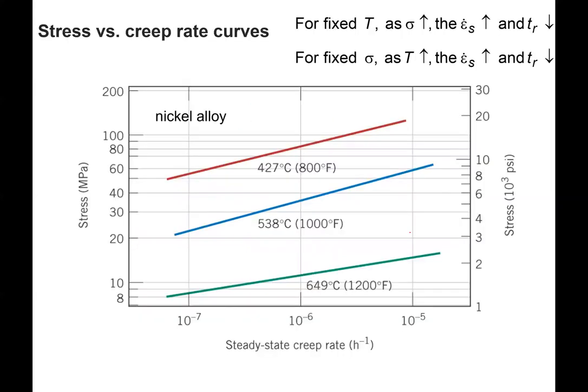So here's some data curves just for that secondary creep rate, where we've got that steady state creep value. Here we're looking at now the steady state creep, so that slope that we have there, versus the stress that's applied to a sample. This is a nickel alloy, also as a function of temperature. So you've got both the stress and the temperature in here as a function of creep rate.